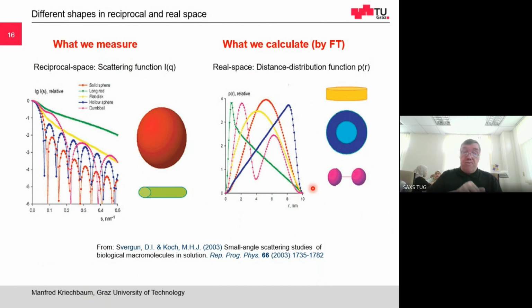curve. So what I want to say, what this picture is telling you, is that in the reciprocal space, you have not a real understanding how your structure looks like. Only in the real space function, you have an idea or a clue how the particle might look like. Like what I told you, here the long distances have a maximum at the diameter. So this means this is a hollow particle. Or in this double sphere molecule, you get this pink curve. So you have two maxima. So it consists of two particles of two masses which are a distance apart. So understanding is better in the real space than in reciprocal space.